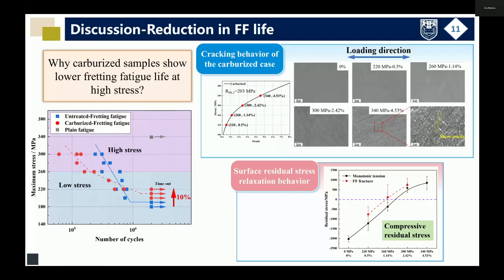So, at the high stress level, the reduction in fretting fatigue life after LTGC is mainly attributed to cracking of the carburized case and the relaxation of the surface residual stress.